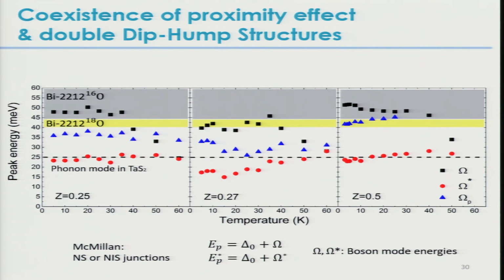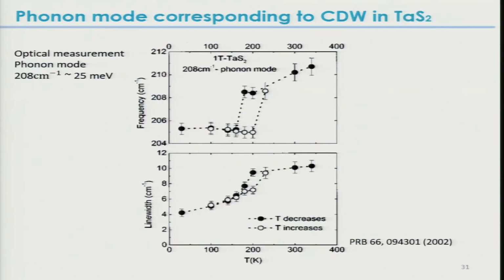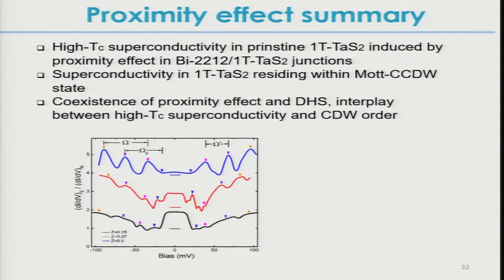I have 5 minutes left. Thank you. And that mode overlaps with one that's seen in transmission optics by David Tanner and collaborators. The 25 millivolts is right here, this phonon mode. So we believe that this is a mode that's involved in that second feature that we're seeing in the spectroscopic data.